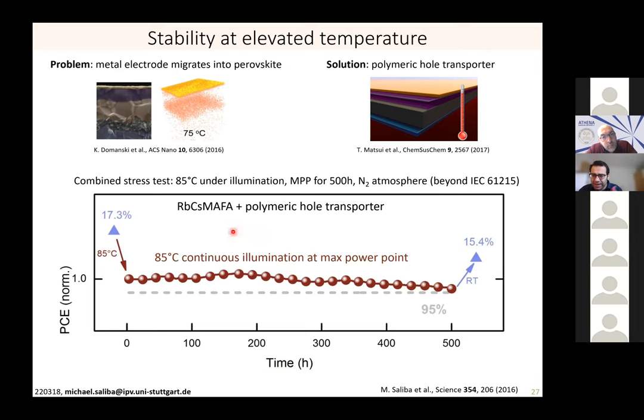Mixing all the knowledge that we had from the previous talks, the best from the previous results, the best perovskite, the best hole transporter, polymeric in nature, we could show that even at 85 degrees, the perovskite device was relatively stable because we could prevent the metal electrode from going inside. This indicated for us, and this was a few years ago now, that the perovskite in principle can be stabilized at least within this harsh environment, and that stabilizing the overall architecture, for example the hole transporter, is an extremely important result, or optimization as well.